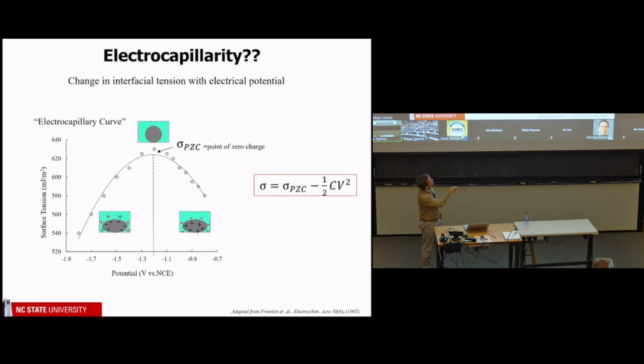But anyway, when you look at this, you might think, like I did, that's great. If I apply a big enough voltage, I can make the surface tension any value I want, including zero. But the problem is, and this is data from 1965, they stopped at this voltage because beyond that the charges start to combine and you get electrochemical reactions. Bubbles form. You might notice that this does lower it from 600 down to 500. That's a pretty big change, but this is still a pretty big tension. So this is not what we're observing.